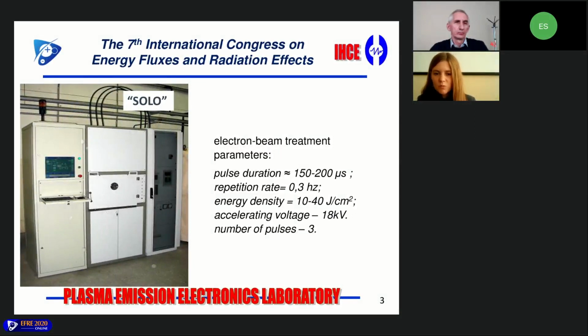The specimens were subjected to pulsed electron beam treatment in the argon environment at a residual pressure of 0.02 Pascal, electron energy of 18 keV, electron beam energy density changing from 10 to 40 joule per square centimeter, pulse repetition frequency of 0.3 per second, and pulse duration of 150 and 200 microseconds.